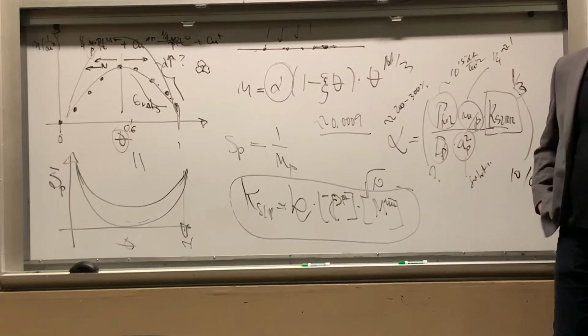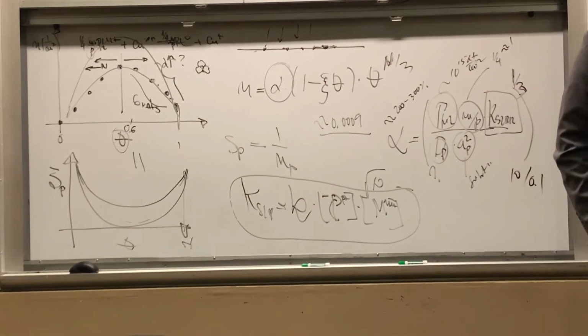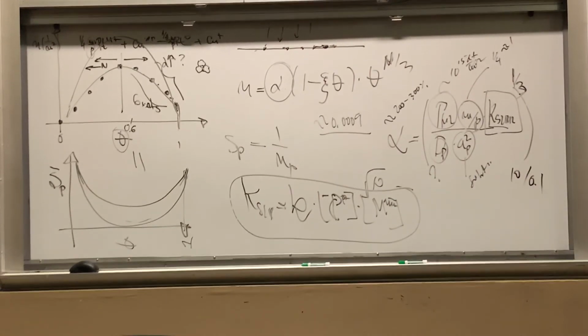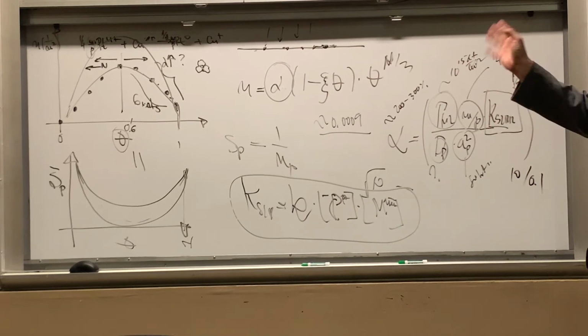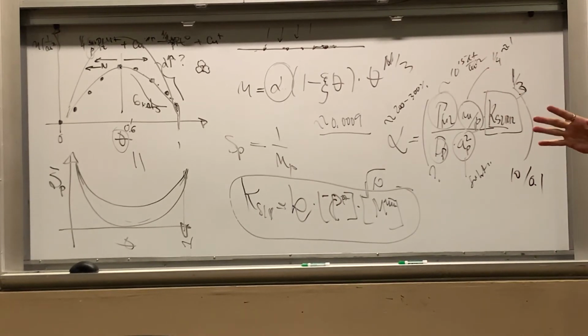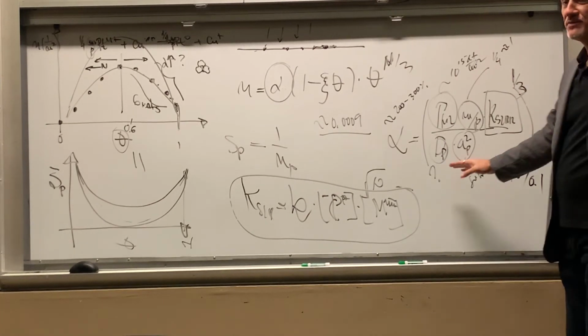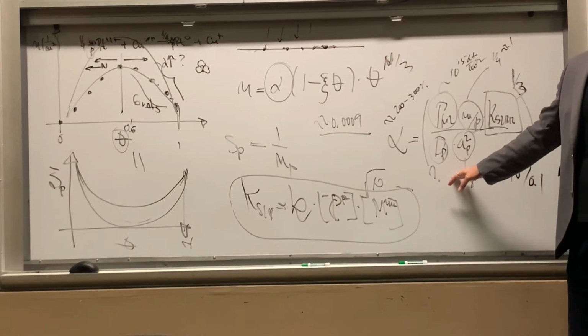And it turns out that the diffusivity of platinum that comes out from the model fit to the experimental data, which is not directly measured but indirectly, is about 3 to 4 orders of magnitude higher than the diffusivity of platinum on the same substrate measured.